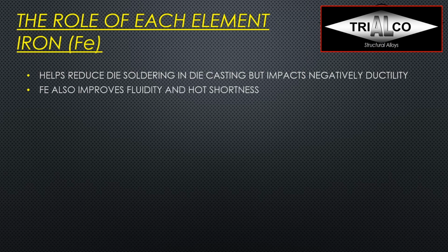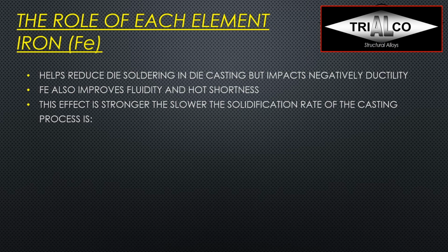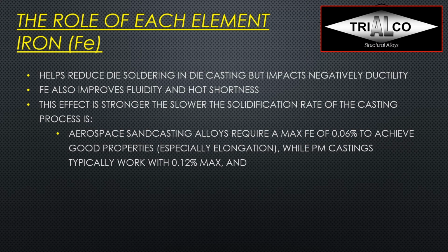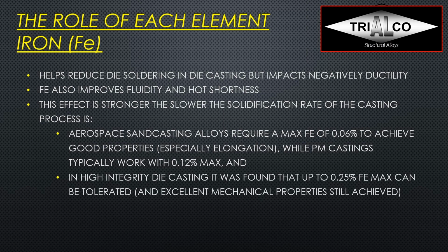Iron improves fluidity and hot shortness, and this effect is even stronger the slower the solidification rate of the casting process. So for aerospace casting alloys, you will find a lot of them specified with, let's say, a 0.06 iron max to achieve very good properties, especially elongation. And for permanent mold, let's say the typical wheel alloy A356, will be specified with ingots at 0.12 max. If you look at high integrity die castings, because they freeze so quickly with very thin walls, they can easily tolerate up to 0.25% iron. Iron also improves fluidity and hot shortness, and as I said before, this is used in certain alloy types that use iron as an alloying element.